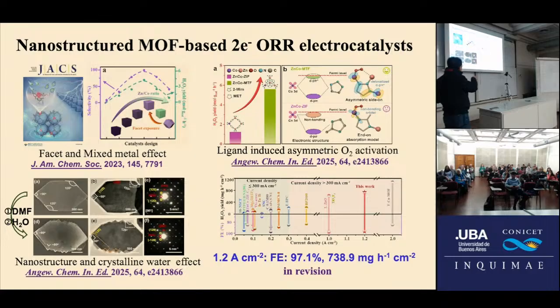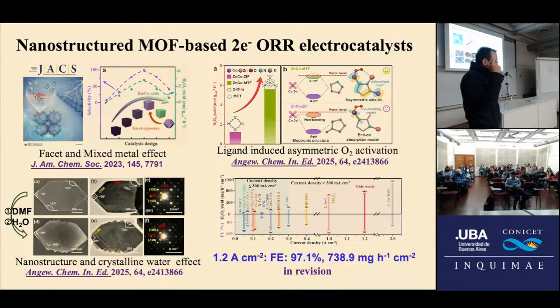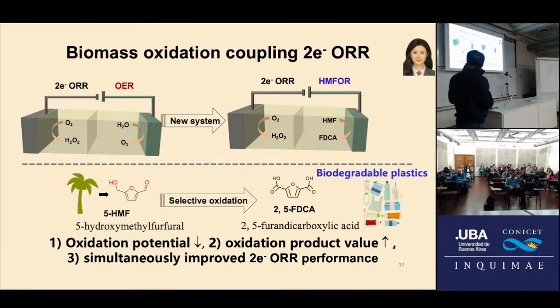And this also demonstrates that increasing the water content is important in this electrocatalyst towards the hydrogen peroxide direction. And we have currently reached a high level of hydrogen peroxide production, reaching this value, and also with close to 98% selectivity. So previously I mentioned the so-called anisotropic electrocatalyst design.